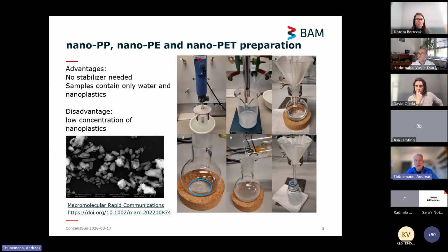We start with a few grams of the polymers. Then we grind them in acetone at low temperature, typically minus 20 degrees Celsius. Then we filter it, add water, remove the acetone, and filter it again. And then you have nanoplastics in water, and these particles are not spherical. As you can see here in the SEM picture from Dan's group, the surfaces of these particles are very rough, and we believe this is relatively close to what we find in the environment.